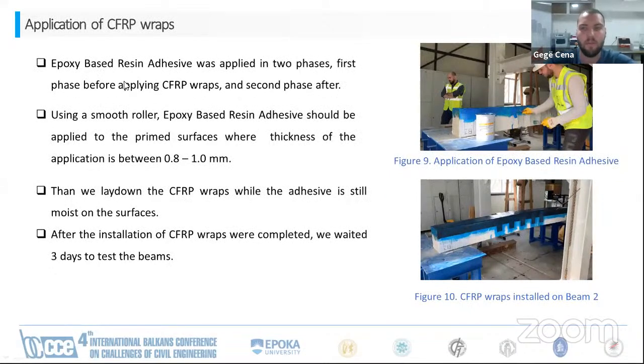The application of CFRP wraps. So epoxy-based resin was applied in 2 phases. First phase before applying CFRP wraps, and second phase after we applied them. Then we used a smooth roller to apply with a thickness of 0.8 to 1 millimeter. Then we laid down the CFRP wraps while the adhesive was still moist on the surfaces. After the installation of CFRP wraps was completed, we waited 3 days to test them because they had to be strengthened.